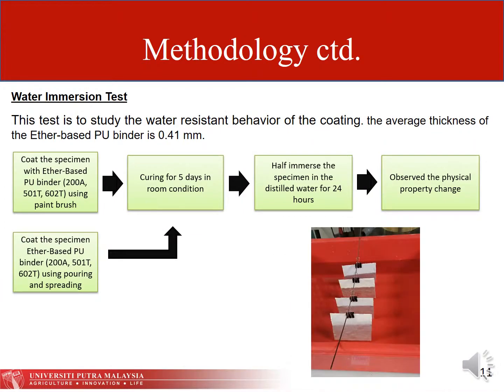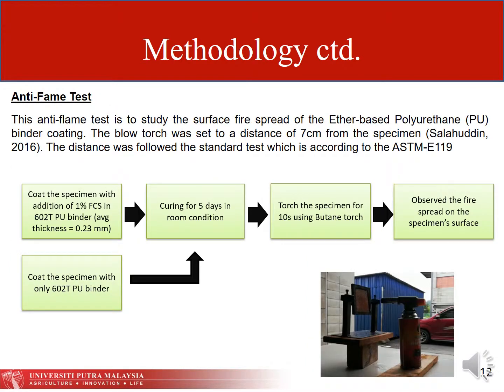For the water immersion test, the average thickness of the ether-based PU binder is around 0.41 mm. First, coat the specimen with ether-based PU binder using a paintbrush, then cure for 5 days. Next, half-immerse the specimen in distilled water for 24 hours as the figure shows, then observe the physical property changes. Repeat it using the same method but a different method of coating, which is pouring and spreading. For the anti-flame test, this test is to study the surface fire spread of the ether-based polyurethane binder coating.